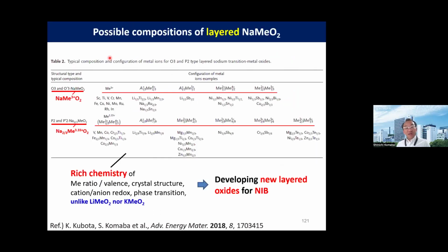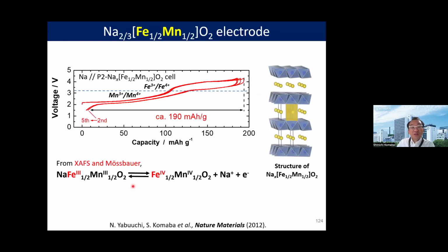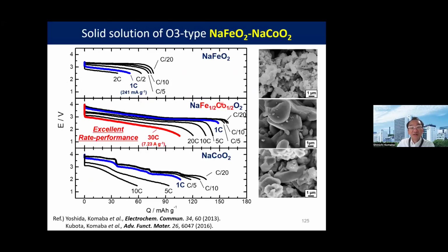Because of the wide variety of crystal structures, we can also achieve very different compositions for the 3 plus trivalent transition metal, and also a mean oxidation number of 3.33 for the P2-type structure. And from this table, you see that rich chemistry exists for sodium layered oxides. One typical example is layered iron manganese oxide based on the 3 plus, 4 plus redox couple for both manganese and iron. Then highly reversible capacity can be achieved in a sodium half cell.